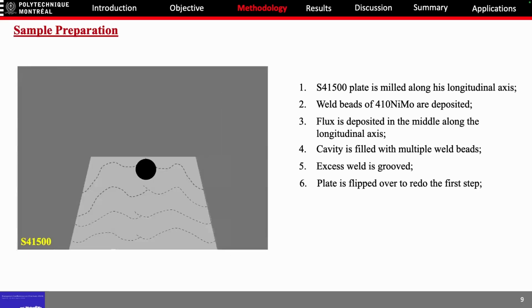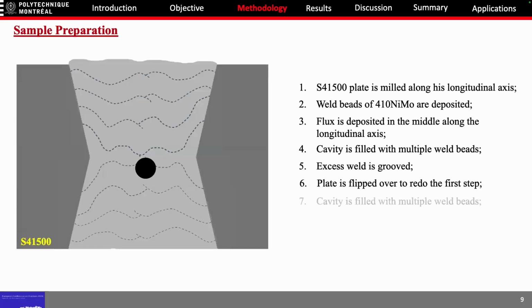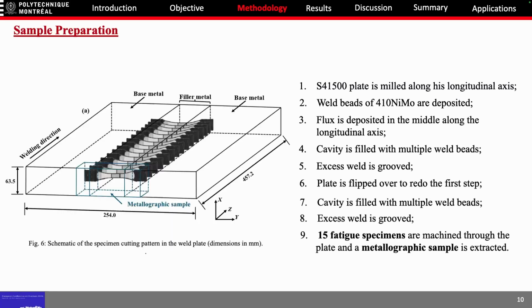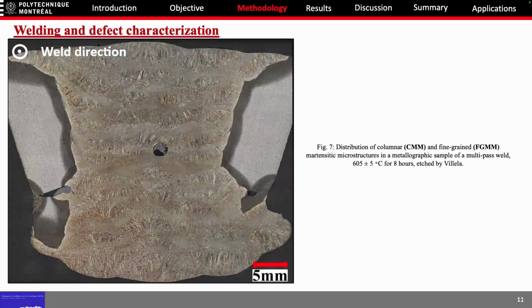The same steps are done once over: cavity, multiple weld beads, and then finally the excess is gouged. From there, a post-weld heat treatment is done at 605 degrees Celsius for 8 hours, and 15 fatigue specimens are machined through the plate, with a metallographic sample extracted from it.